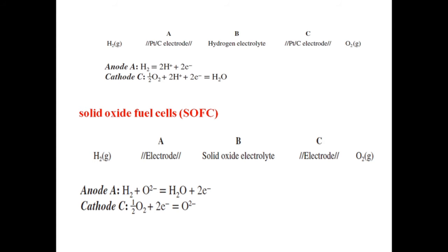Under these conditions, many oxides would be reduced, liberating electrons and thus leading to unwanted electronic conductivity. The cathode materials used have to conduct both oxide ions and electrons satisfactorily, but in addition, for compatibility, they must have a similar thermal expansion coefficient as the electrolyte. The strontium-doped perovskite, LSM, is one of the materials of choice.